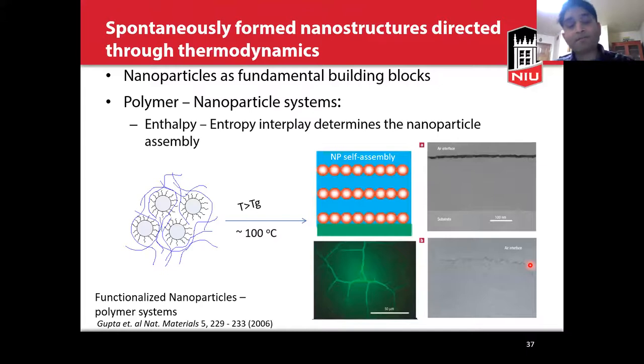People have done that, at least in terms of demonstrating the assembly of nanoparticles, providing them with the right conditions. People have demonstrated that before. So the idea here is you take nanoparticles, a two-component system. You have nanoparticles and polymers, a mixture of these particles and polymer. You deposit that as a thin film, and then heat it. And through thermodynamic-driven segregations or thermodynamic-driven processes, these nanoparticles can be made to self-assemble into these ordered structures like these,